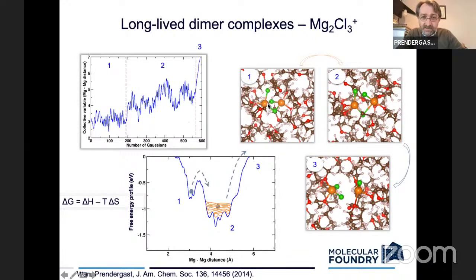What we found was that that species, when you first form it, is only short-lived. And eventually, if you break them apart, 2 chlorines go with 1 magnesium, 1 with the other. That's maybe to be expected. But there's this intermediate, which has 1 bridging chlorine and 2 dangling ones that seems to have a deep minimum in free energy. So it's getting more complicated. We need a little bit more heuristics here to try to understand how these electrolytes behave.